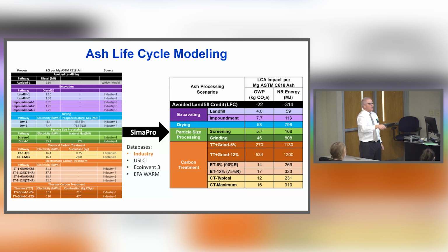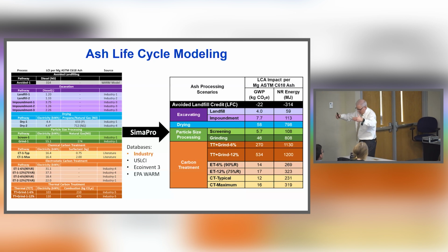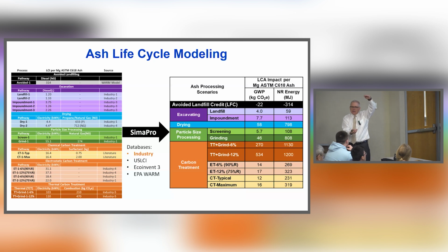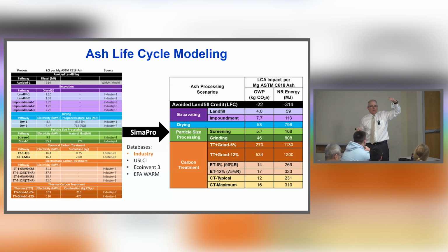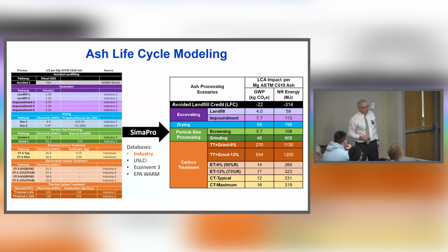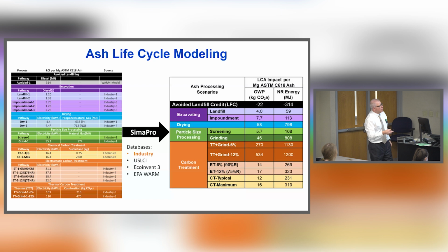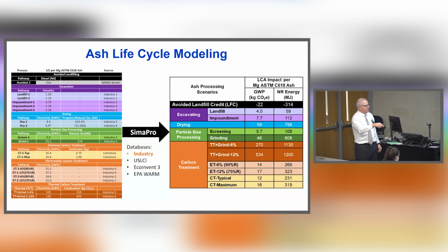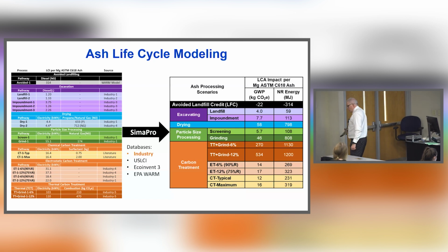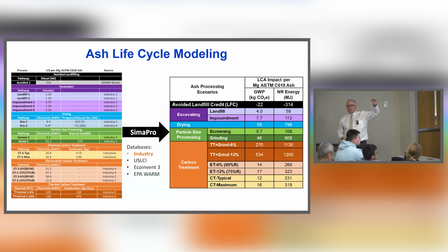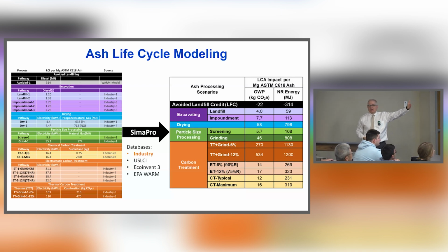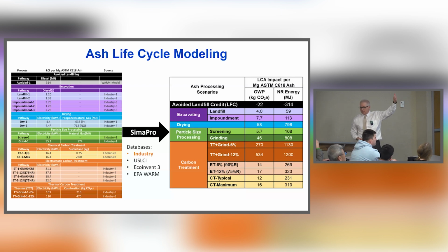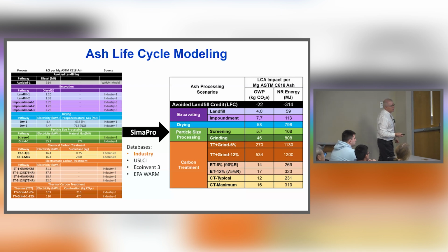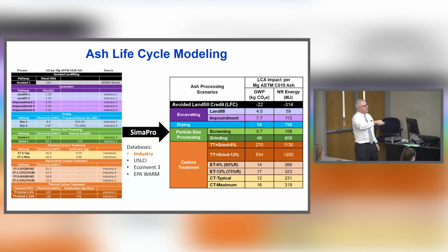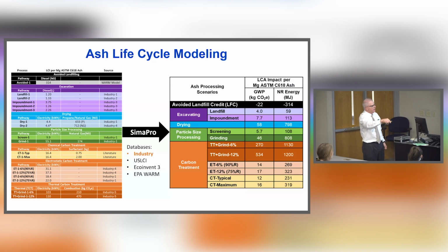We used another thing called electrostatic treatment. So essentially, we run the ash on a conveyor belt, which has charges on two different sides, all right? And essentially, by that charge difference, it will pull the carbon particulate out of the ash. That's electrostatic. Not quite as efficient a carbon removal as I get with thermal treatment. And then there's another technique called chemical treatment, where I apply essentially a surfactant to the ash, and it bonds onto the carbon surfaces, blocking those surfaces for interaction with, for example, air entraining agents in a cement. So I could do chemical treatment, electrostatic treatment, or thermal treatment. And again, we did all the analysis for each one of these.